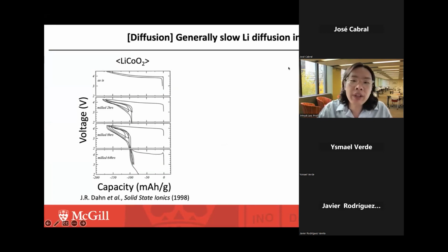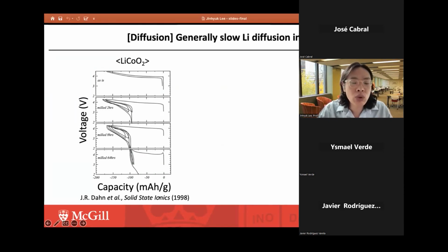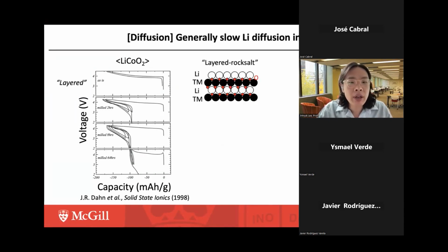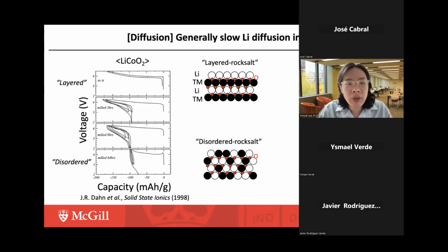So historically, these DRX materials have been neglected as cathode materials for a very long time because they tend to show very poor performance. For example, here I'm showing you the voltage profile of lithium cobalt oxide on the left side as the structure changes from the layered rocksalt structure to the disordered rocksalt structure by a process called cation disordering.